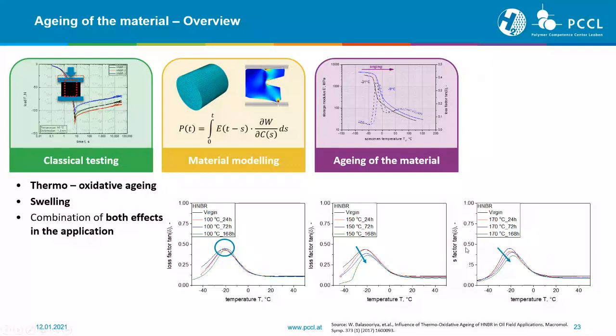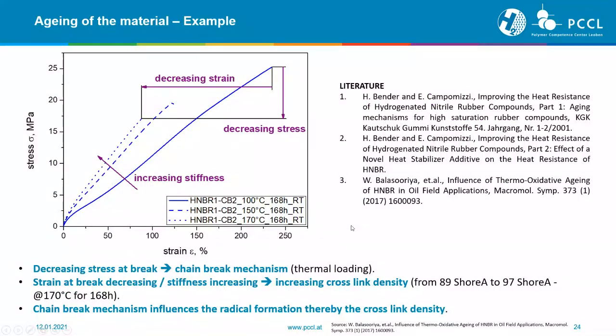But we see this not only in our dynamic mechanical characterization, which represents the network or the damping capabilities of the material. We see it also, for example, in stress-strain curves. I'm showing you just 3 examples: maximum aging time, always the same with 168 hours, applied at 100, 150, and 170 degrees C. And what we've seen here is the virgin curve ending up with a strong increase of the stiffness, a clearly decreasing strain, and a strongly decreasing stress. And this just with 168 hours for an HNBR, which is usually applied for high temperature applications.